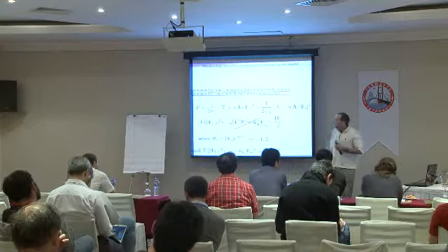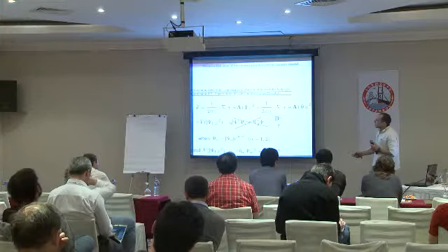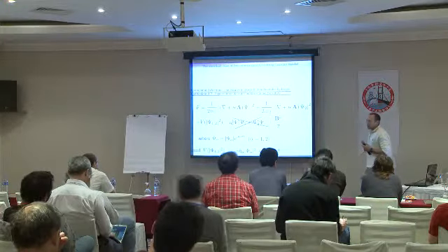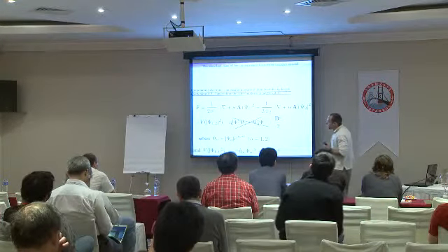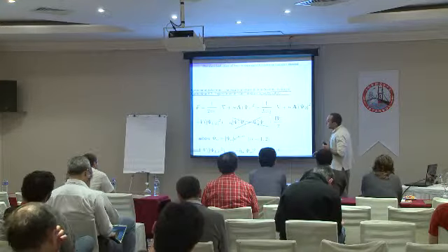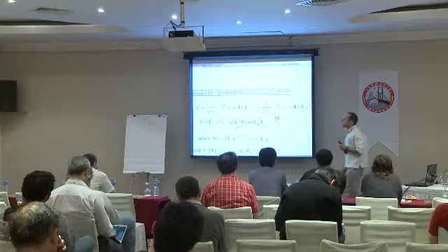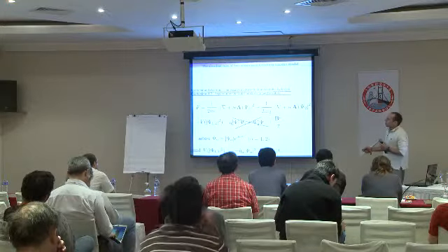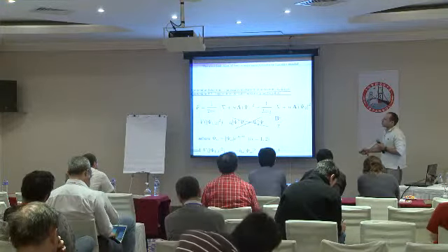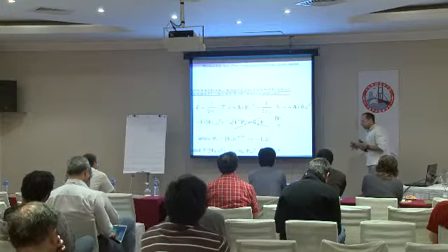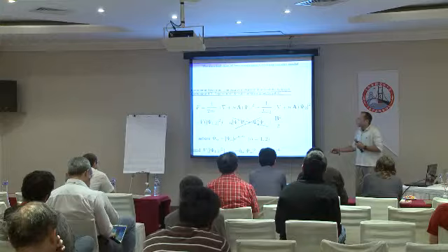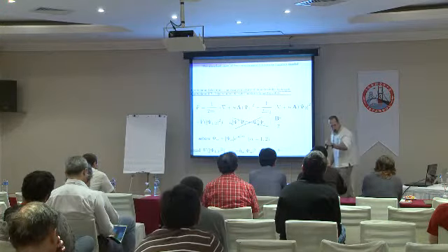In that case, you have electronic Cooper pairs and protonic Cooper pairs, and since you cannot convert electrons to protons, you have intercomponent Josephson terms strictly forbidden on symmetry grounds. Then your condensates are coupled only through the vector potential. There could also be some different kinds of couplings, like drag coupling, but no intercomponent Josephson coupling. And let me start with